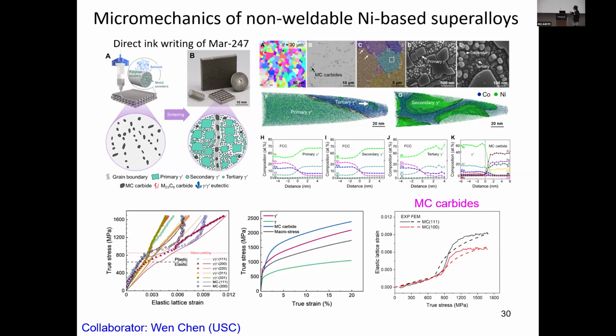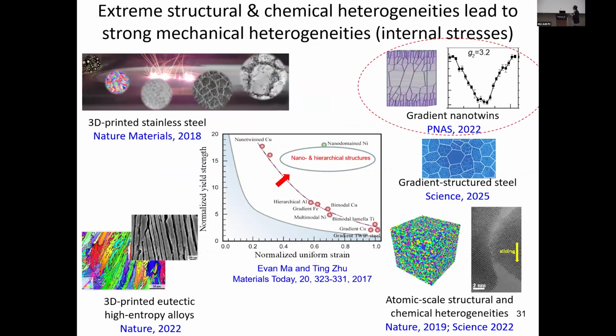So with the synchrotron experiment, we can track the internal strain and stress evolution for different phases, and also for the carbides. Carbides, on one hand, can reveal their own deformation behavior through the synchrotron result, and can also act as an embedded sensor to reveal the internal strain evolution within the different grain families. So this really provides a very powerful way of characterizing and understanding this complex internal strain and stress evolution.